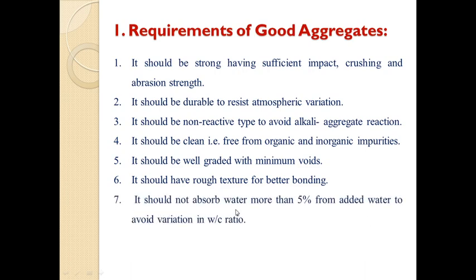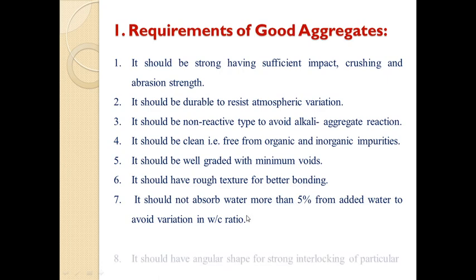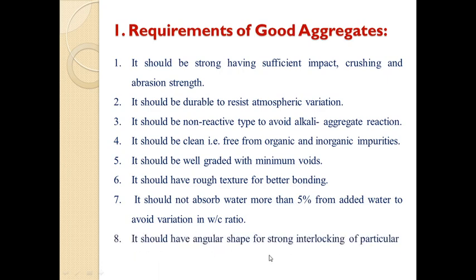The aggregate should not absorb water more than 5% from the added water, to avoid variation in the water-cement ratio. If aggregates absorb more than 5% water, they can absorb water from the cement paste, making the concrete mixture harsh. Also, it should have an angular shape for strong interlocking of particles.